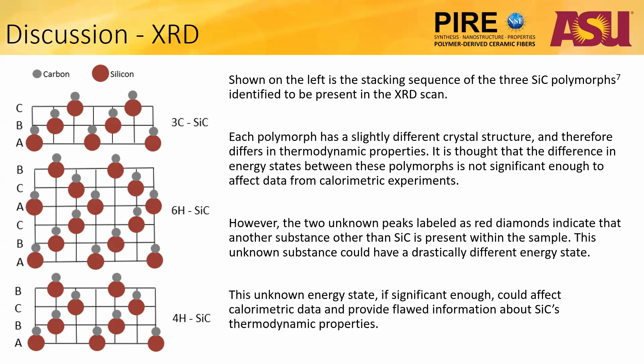As shown previously in the XRD results, the sample is mostly silicon carbide containing three common polymorphs: 3C, 4H, and 6H. Each polymorph has a different symmetry and crystal structure, which also implies that their energy states are different. Currently, it is thought that the different SiC polymorphs present in a sample are by themselves not enough to significantly change the sample's heat of formation during calorimetric experiments, because although their energy states are different, they are thought to be very close to each other and would not affect results.